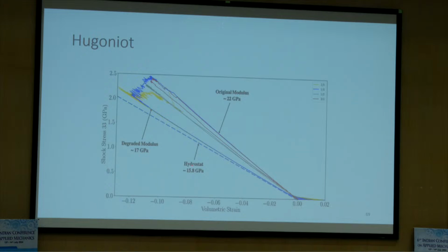Hydrostat is the pressure volume equation of state. It's 15.8 is the bulk modulus in the hydrostat. Whereas the slope of this is not square root of k over rho. It is the square root of k plus 4/3 g over rho, okay? So the wave speed under uniaxial strain is different than the wave speed under uniaxial stress, is different than the wave speed under spherical wave. So you have to be very careful when you try to understand. So it's beautiful. The model is nicely taking in the original modulus, degradation of the modulus, and eventually it is reaching the hydrostat.